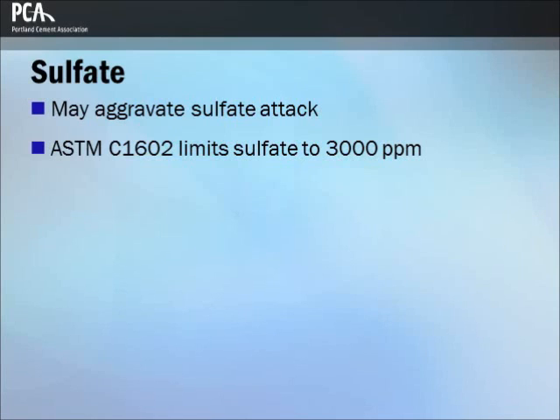Concern over a high sulfate content in mixing water is due to possible expansive reactions and deterioration by sulfate attack. Although mixing waters containing 10,000 ppm of sodium sulfate have been used satisfactorily, the limit in ASTM C1602, 3,000 ppm, should be considered unless special precautions in the composition of the concrete mixture are taken.